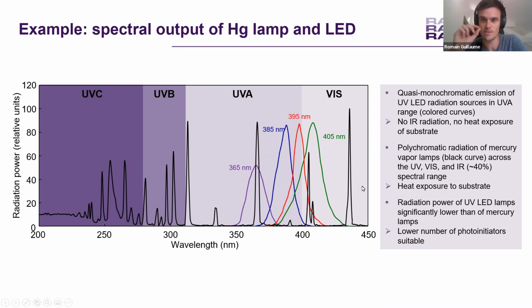With LED, we have quasi-monochromatic emissions, so we have to find formulations which fit perfectly with this kind of photons, which is not the case with mercury lamp. As it's broad, the formulation will almost always find a photon suitable for it to react. So that's the main difference. But a good advantage is also that the LED doesn't emit infrared radiation compared to mercury lamp. So again, we have no, or at least less, heat exposure on the substrate itself.